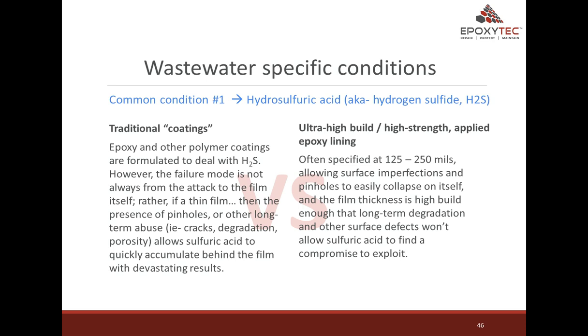Versus high build, high strength applied epoxy lining, often specified at 125 to 250 mils, allowing surface imperfections and pinholes to easily collapse on themselves. And the film thickness is high build enough that long-term degradation and other surface defects won't allow sulfuric acid to find a compromise to exploit.